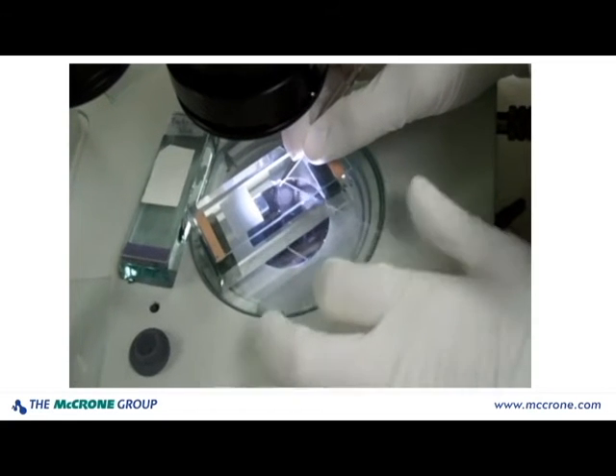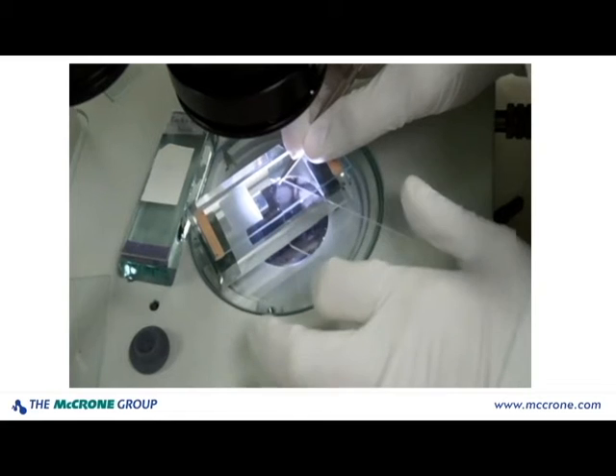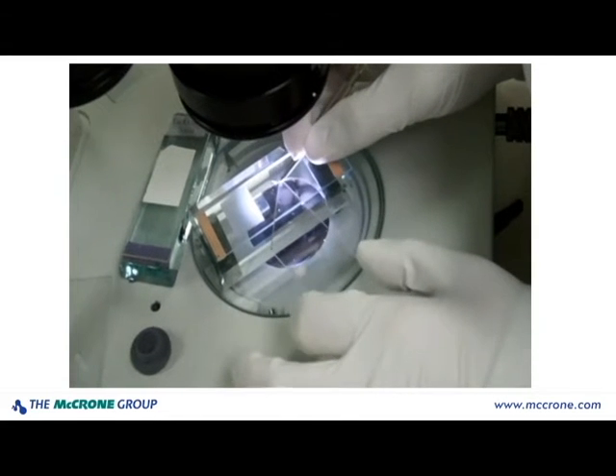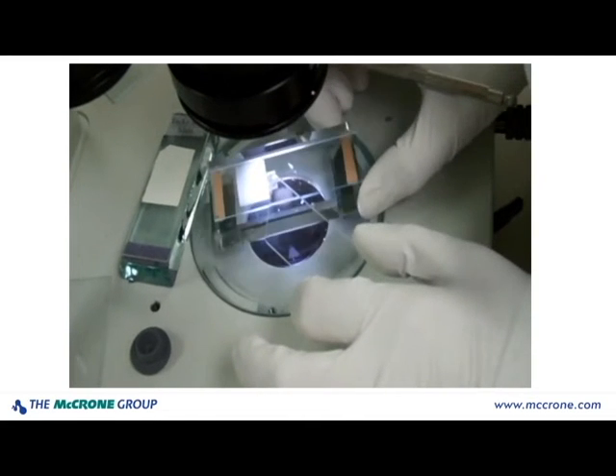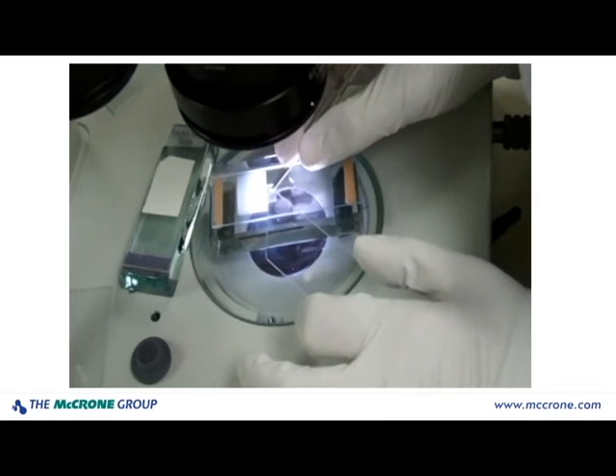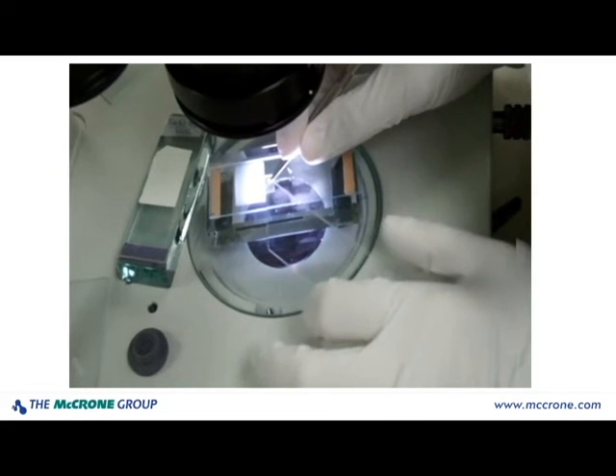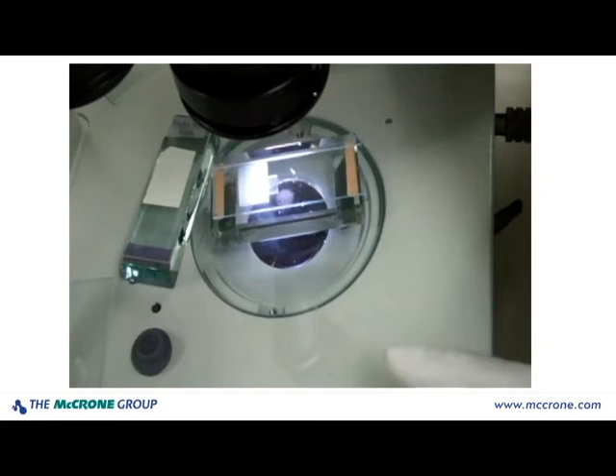Now if you're lucky, sometimes your sample sticks to the wedge itself. And in that case, the wedge can then just be transferred to the micro KBr crystal, and you can apply pressure with the carbide scribe, transferring your sample to your KBr crystal.